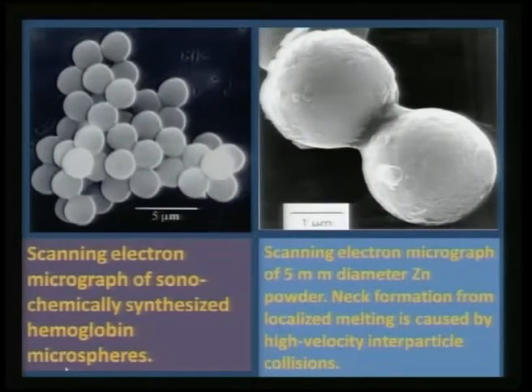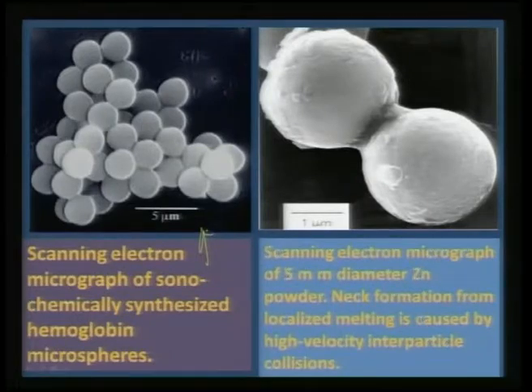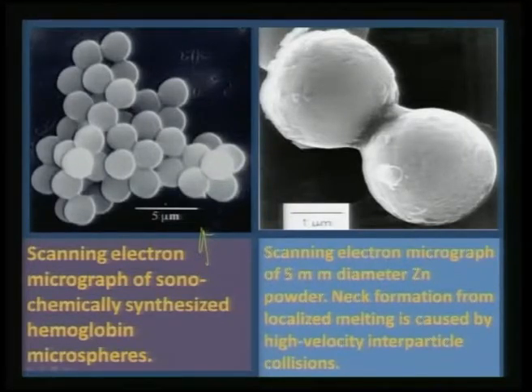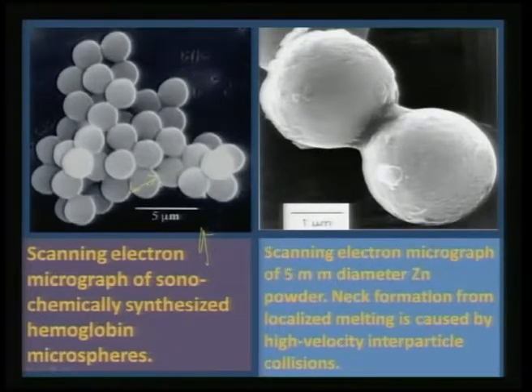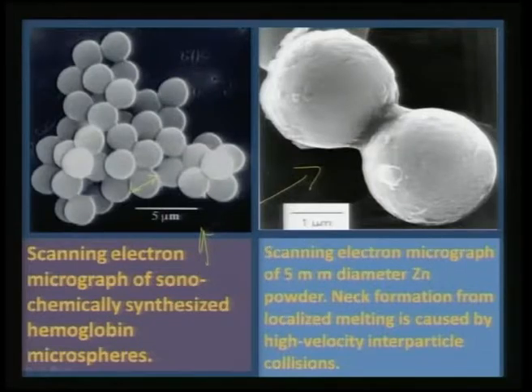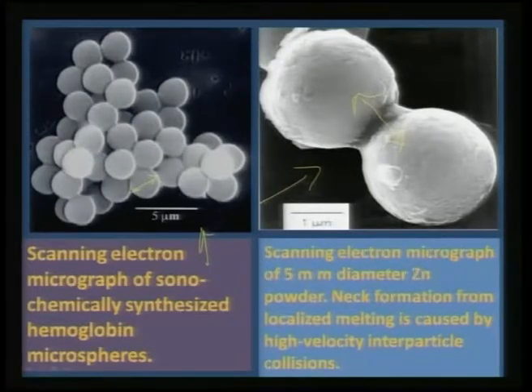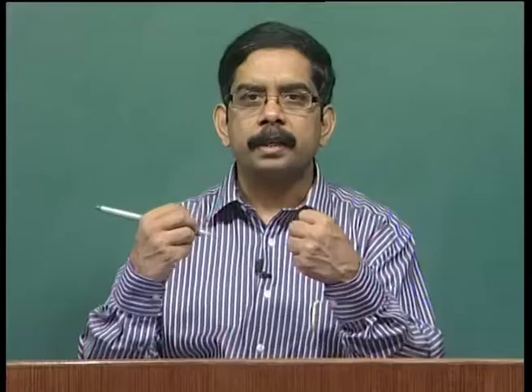Sonochemistry has gone well beyond simple synthesis. This cartoon shows you can make mono-sized hemoglobin microspheres using sonochemistry — roughly 2-micron particles of very uniform spheres. Here is another cartoon of zinc powders: if you sonicate zinc powders, you can see welding happening between two zinc particles. Essentially, there is localized melting and high-velocity inter-particle collisions happening between two particles, which clearly shows the energetics involved in ultrasound.